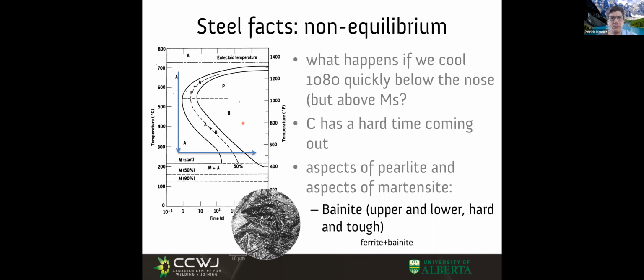So we're going to be calling them bainitic microstructures, but not just bainite, because often when people say bainite, they refer to something very particular that looks like this. But in welding, things can look very different, and still be this mixture—a little bit of diffusion for the transformation and a little bit of displacement too, like a hybrid of martensite and pearlite. Okay, now what do we know? We know the start of the transformation, the end of the transformation, and the effect of time on both.